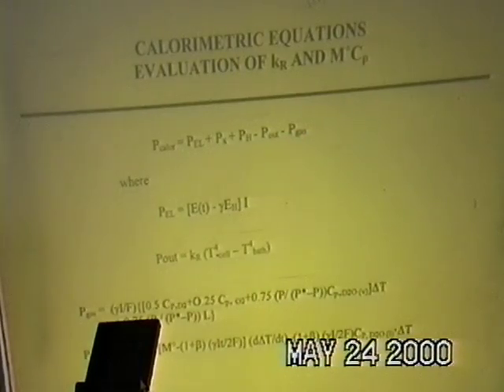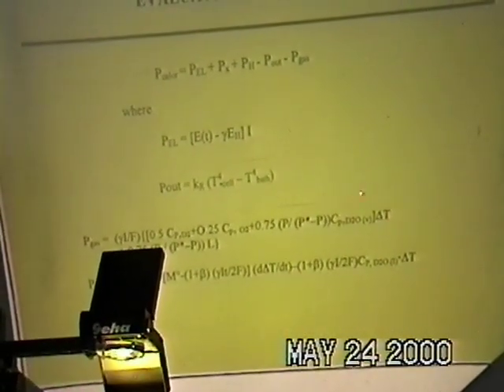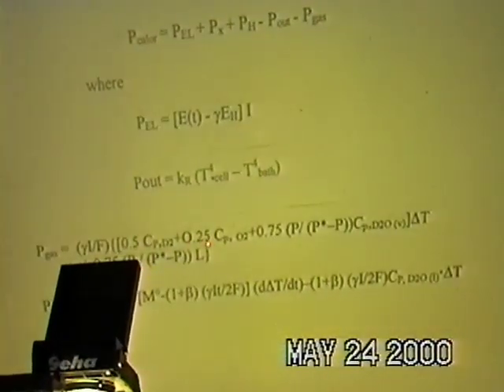So that is your equation, but the terms get rather complicated. That's the electrical power in, that's the thermal neutral potential, the Faraday efficiency, which is 1 in all cases that I've ever run. The power out, since this radiative transfer is T to the 4th, and the radiative heat transfer coefficient. The power of the gas stream is rather complicated, but involves heat capacities of the various gas species, deuterium gas, oxygen gas, D2O vapor leaving the cell, as well as the largest term, actually, which is the power lost by evaporation, D2O changing from liquid to gas. That turns out to be the largest term there. The power of the calorimetry is this term right here.